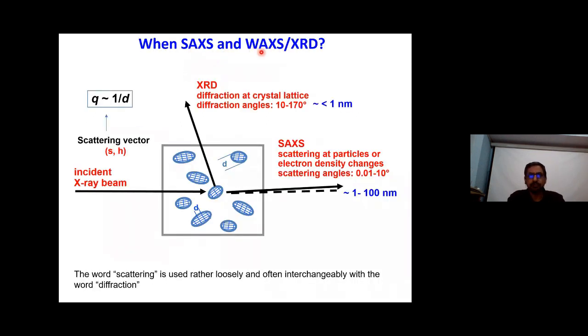So what is small angle X-ray scattering, wide angle X-ray scattering, or XRD? Here Q is known as the scattering vector. It's related to theta in normal diffraction language, but it has all the information about the wavelength of the X-rays used and the angles. Q is inversely proportional to d. As Q decreases, you are looking at very large d values, 1 to 100 nanometers. When Q is high, as in XRD, 10 to 170 degrees, we are looking at much smaller dimensions. Basically, we are interested in small angle X-ray scattering, so we will look at only the small angle region.